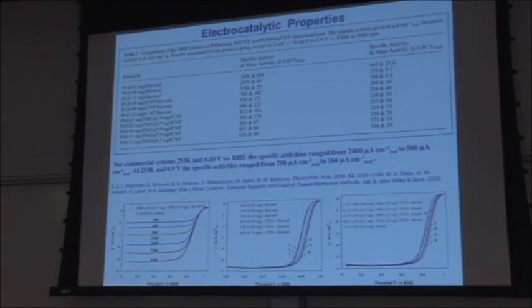So what we did is we actually compared our platinum on carbon nanotubes and platinum with niobium oxide carbon nanotubes to commercially available electrocatalysts. So this is straight out of literature from various sources. And what we find is that our materials are not on the high end of mass activity and specific activity, but they're on par.